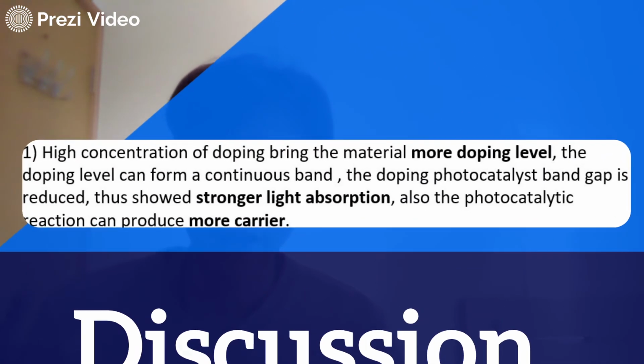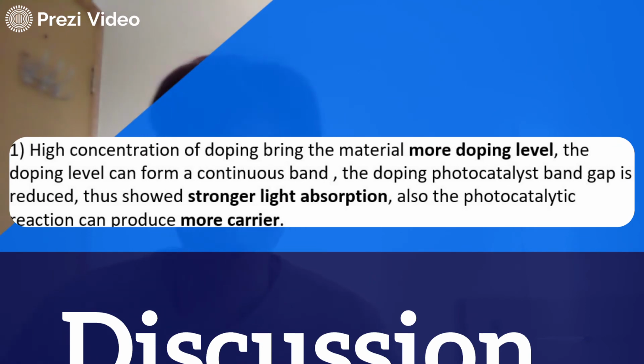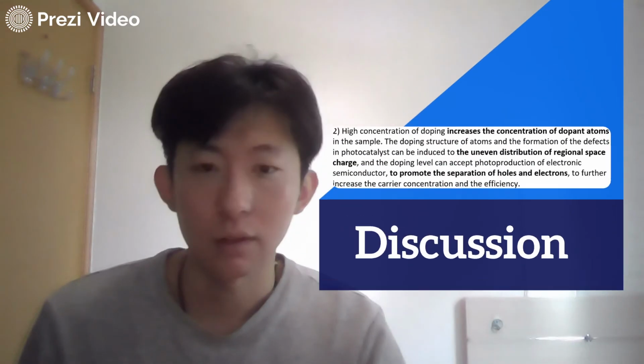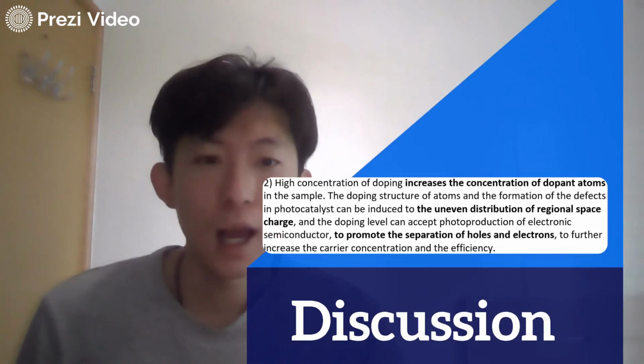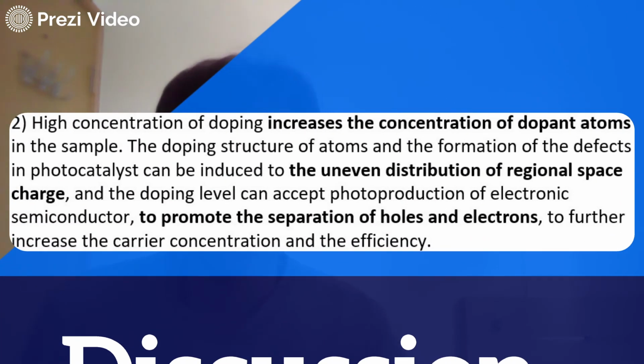First, high concentration of doping brings the material more doping levels, or even forms a continuous band. The band gap is reduced and the photoelectrons are easier to form, so the carrier density is higher. Second, higher doping could form more doping structures and defects, which could induce an uneven distribution of regional space charge. So the separation of holes and electrons is promoted. Thus, the carrier efficiency is higher.